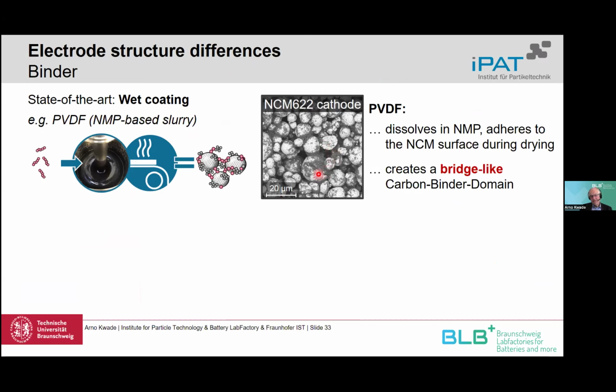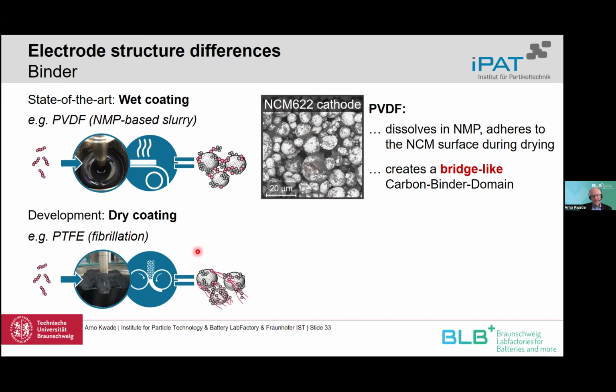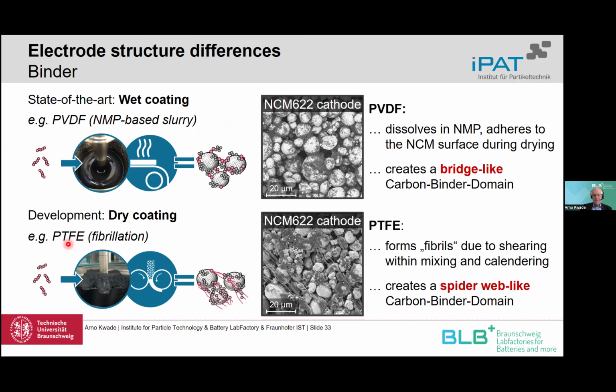Maybe one word as a comparison to the wet process. Here you see a surface of a wet processed electrode. You see that we have this carbon black binder domain, which is really at the connecting points between the particles. And this is more bridge-like connections, particle bridges we have. If we go to this dry coating, we have this PTFE, which forms nice fibrils, so particles which have a really high aspect ratio. And these fibrils, which you can see here really nicely, they connect our particles and also the particles with the carbon black. So it's more a spider web-like domain.